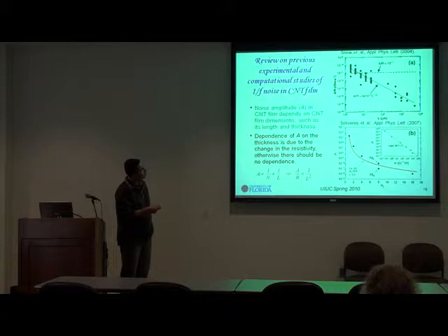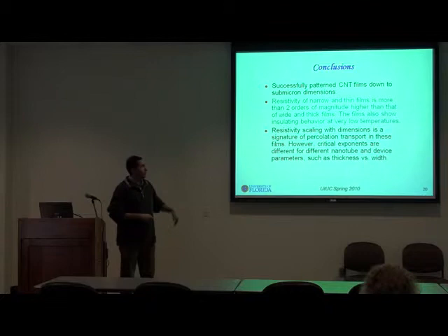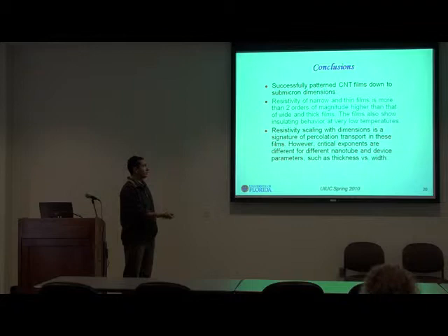And also, people have followed it up with other dimensions like the effect of thickness, the number of layers, same thing. And people have seen a significant increase in the noise amplitude that seems to not only scale with the thickness, but also scale with the resistivity level in this material. So basically, you're changing one parameter like the thickness, but there is an effect due to that thickness, and there is also an effect from the change in resistivity. So I will come back to this when we go further. I will try to explain how we try to model these effects into our computational modeling approach.